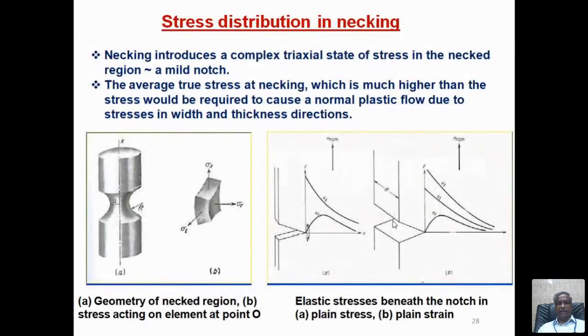And the necking stress distribution, how is the stress distributed in the necking? Because two types of things will happen. If it is a thin specimen, you see the elastic stresses beneath the notch. At the notch, the stress will be maximum, at the tip of the notch. You are making a notch. It may be a sharp notch, a V notch, or a blunt notch, whatever the notch is, at the tip of the notch the stress will be maximum because of stress concentration. Stress concentration is higher at that point, so maximum stress will be there.